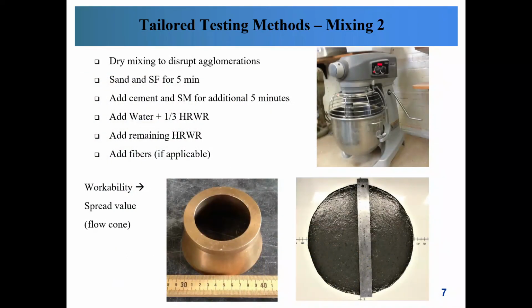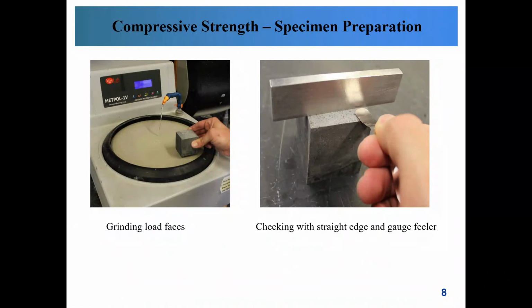When mixing UHPC, we usually used the tabletop mixer displayed here and followed a strict mixing protocol for enhanced consistency, as listed here. The workability was measured by the spread using a regular flow cone. Compressive strength has been tested using 2x2 inch cubes. Prior to testing, the loading faces were ground until passing the quality control.